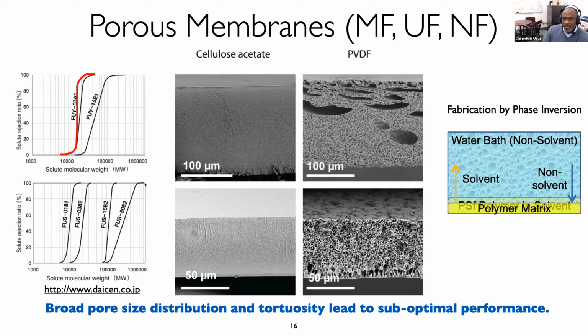And so here I've just highlighted the structure of these membranes for microfiltration, ultrafiltration, and in some cases nanofiltration that are produced by non-solvent induced phase separation, right? And so the manufacture of these membranes is quite simple and straightforward. It involves entry of a non-solvent, in this case water, into a concentrated polymer solution or a dope that's spread as a thin film. And the entry of that non-solvent into this concentrated solution results in a precipitation of the polymer in a random tortuous structure that has an average length scale that can be used for separation.